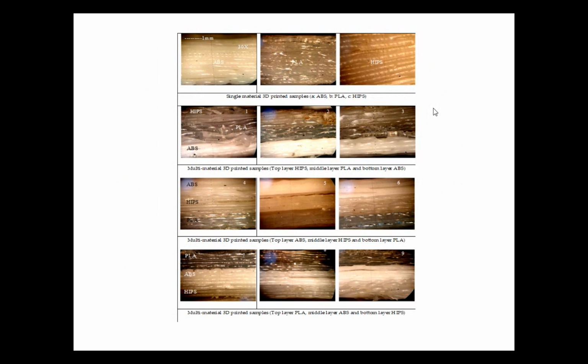Now you see in this diagram, I have seen the morphology of the printed section. That is really important. One of the limitations of 3D printing is that we have a staircase effect, right? If you see this picture, in the top layer I have the single material ABS. I am seeing it at 30x magnification. This is of PLA and this is of HIPS. You can clearly see that in all the materials, even though this is a single material, I have a staircase effect. You can see the layer by layer printing, and I have a staircase effect.